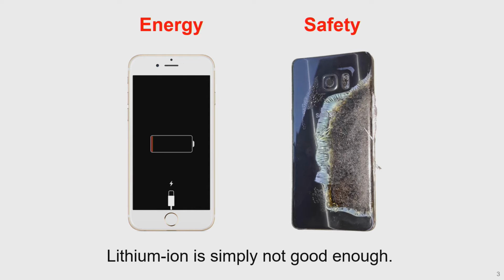What they're projecting for their baseline vehicle is a battery pack at 300 watt-hours per kilogram, which means realistically you're talking about a cell level specific energy of 350 or 400 watt-hours per kilogram easily. And you have to do that while being able to deliver extremely high power and to do all that in a profile that is not sensitive to heat generation and doesn't suffer from thermal runaway and other thermal abuse issues. Because essentially when you're running these eVTOL vehicles, for instance, they are extremely aggressive on battery operation.